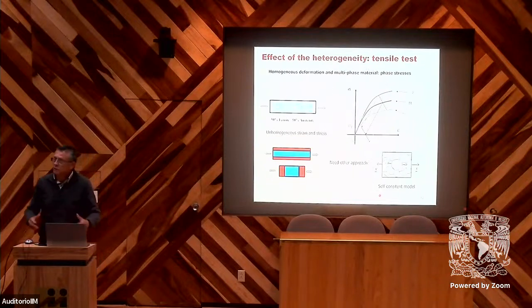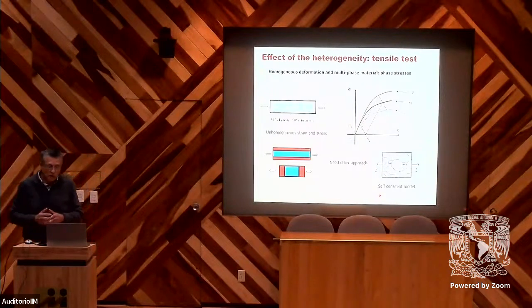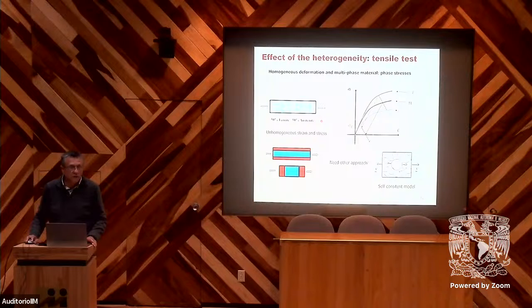But in other cases, for example, if we consider duplex steel, a multi-phase material with austenite and ferrite. In this example, we can have 50-50%. And here the ferrite is harder than the austenite. So when we make loading during the tensile test, you will have higher stress in the ferrite than in the austenite. And when you unload, you will have tensile stress in the ferrite, and this will be equilibrated by compression in the austenite. But the calculation of this will be more complicated because we are not in the case of homogeneous strain or homogeneous stress. So for this, we need a more complex model. We use here, for example, a self-consistent model to make all calculations.